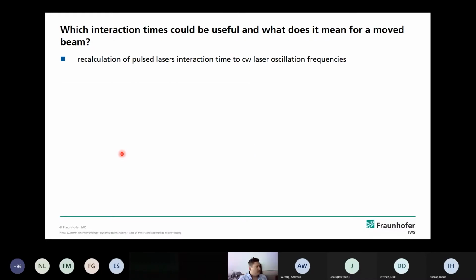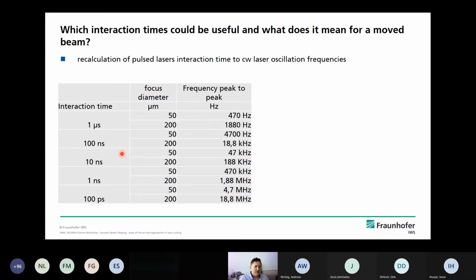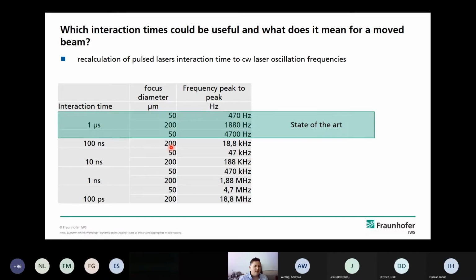You see here this table. I tried to calculate the interaction times for significant beam diameters. So 50 microns should be possible with the CW laser. 200 micrometers is a common focus diameter for laser cutting. And if we are talking about our current state of the art, that means using a galvo scanner, we are able to operate maybe in this field, with an interaction time around 1 microsecond or even below.